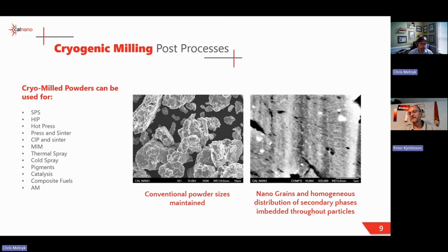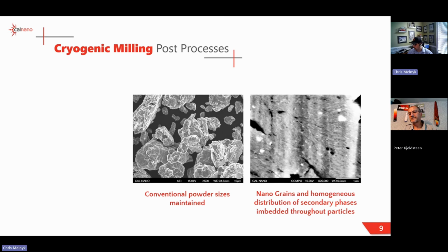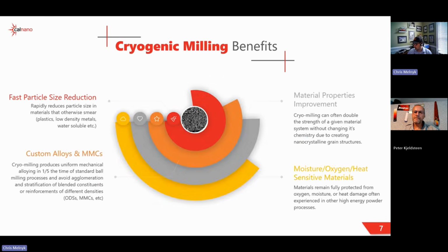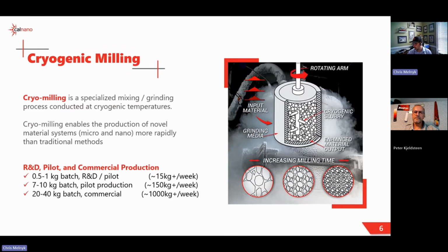And again, that depends because the amount of media, the way I had that picture there, the media to ball ratio is going to dictate. There's a volume limit in there. So the tap density of your material matters. If you're processing tungsten, you could probably fit 100 kgs in the bottom half of that mill. When you're processing magnesium, it's a lot less. So that affects it. And then of course the ball to powder ratio, as we call it, has a huge effect on everything else as well.